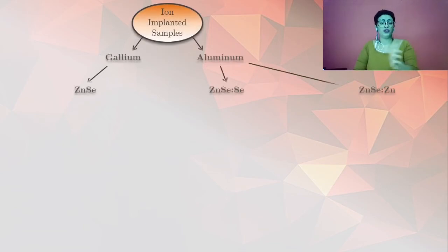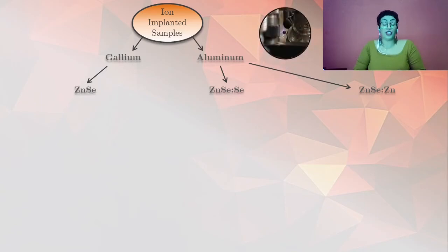In parallel with the diffusion doping process, one of each mother sample was submitted to doping with gallium and aluminum by ion implantation. The ion-implanted samples just become luminescent after heat treatment, performed at 400 Celsius degrees during 1 hour. This is because during the implantation process, the atoms penetrate the material in arbitrary positions, destroying the lattice. So it's necessary to perform a heat treatment to restore locally the lattice and increase the mobility of the vacancies and impurities to allow the complexation of defects which the yellow-red luminescence characteristic of zinc selenide is associated to.